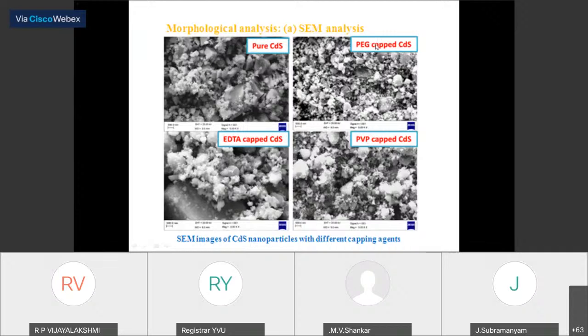In this one, we have the PEG capped nanoparticles, and here the particles are small. When you observe EDTA, the particles are also big. And when you see the case of PVP, so when you observe all these four diagrams as far as morphology is concerned, we can see that PEG is a good capping agent, suitable for the cadmium sulfide. So we have to check by a trial and error procedure which capping agent is suitable for our material to get the particles in the desired size and shape.